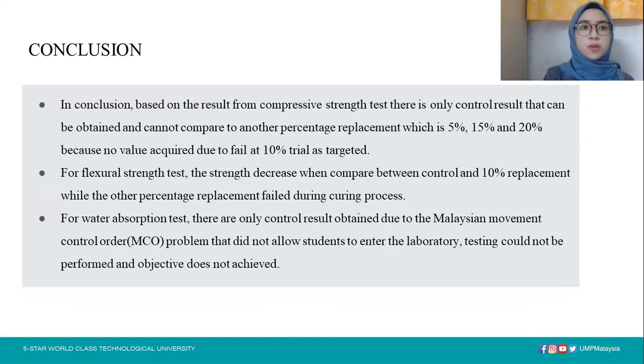Now, I would like to conclude my research presentation. Based on the result from the compressive strength test, only the control result can be obtained and compared to other percentage replacements, which are 5%, 15%, and 20%, because no value was acquired due to failure at the 10% trial target. For the flexural strength test, the strength decreased when comparing control and 10% replacement, while the other percentage replacements failed during the curing process.